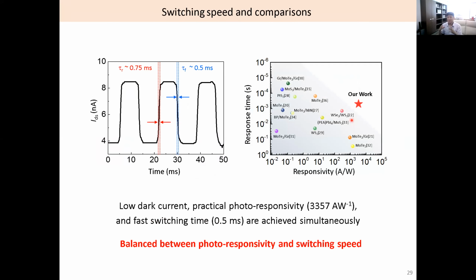Another thing is that the photo-gating effect involves trapped charges. Trapped charges mean very slow dynamics because it takes a long time to escape the trapped state, okay? But in our MoTe2 case, this self-gating, orbital gating case, only the top MoTe2 layer is gated. And then this switching speed depends on the carrier mobility of the electrons. So it is much faster than the typical photo-gating effect, which originates from charge traps. So we take two advantages. One advantage from photo-gating, high efficiency. And the second thing, fast switching time.